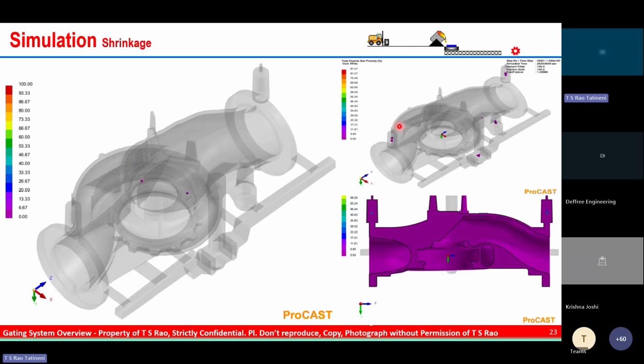The next one is the shrinkage process. You can see the shrinkage points coming up when the part is getting solidified. Again, it depends on the quality requirements of the castings. If you see the geometry at the cut section closely, this casting is well within the color coding of level 2. On a scale of 1 to 100, for our understanding, if it is within 20, it is level 1, up to 40, level 2, up to 60, level 3, up to 80, level 4, and if it is red hot, then it is level 5 shrinkage. When you see the color coding in the cut section, all are within level 2. So from here, we can find out the shrinkage pattern after the cut section.